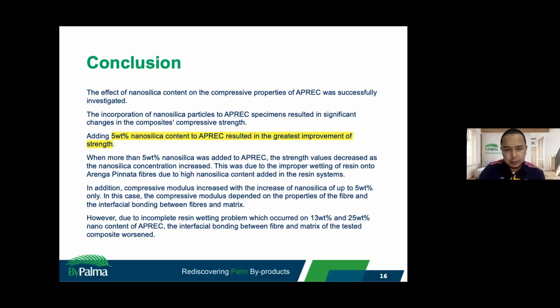results in the greatest improvement of the strength. However, it reduced after we increased the weight percent of nanosilica. This is due to the improper wetting in the composite.